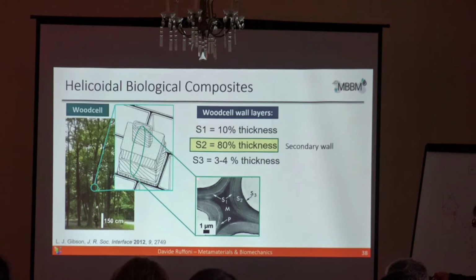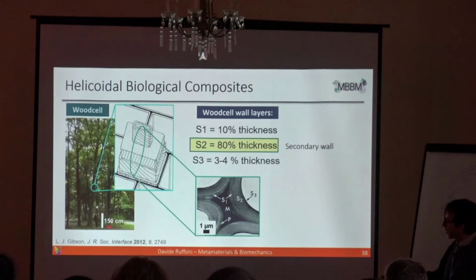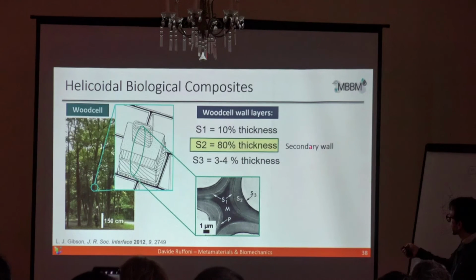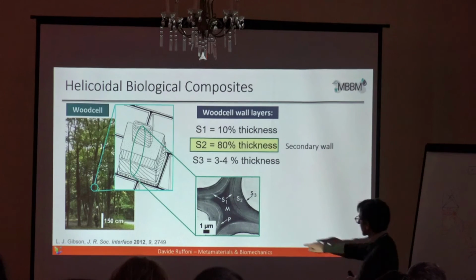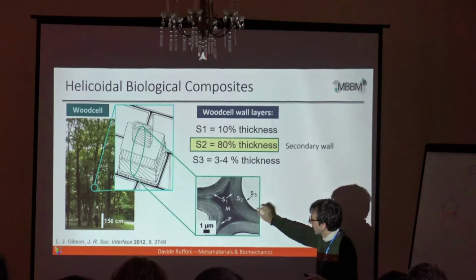And when we look a little bit more in detail at a wood cell, you have to think about wood cells as long cylindrical tubes, which, let's say, in hardwood are empty, and in the wall of this tube you have cellulose which is actually resisting and taking up the load, the weight of the tree. And these cellulose walls are multi-layer, composed actually of 3 different concentric layers. The so-called S2 layer is the secondary wall, the dominant layer in thickness. This is a cross-section of the wood cell. This is the S3 layer, S2 is the thickest, and then the S1 layer is very thin.